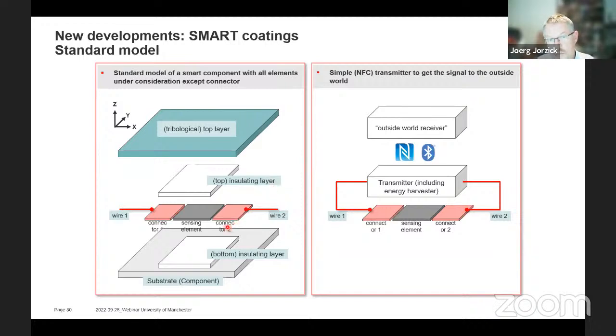In order to allow this, we need to decouple this sensing element from the substrate, because typically this is a kind of metal part. So we need to have kind of insulating layer first before applying the sensor, and then a kind of top layer to cover the sensor, and then we can even add a tribological coating.